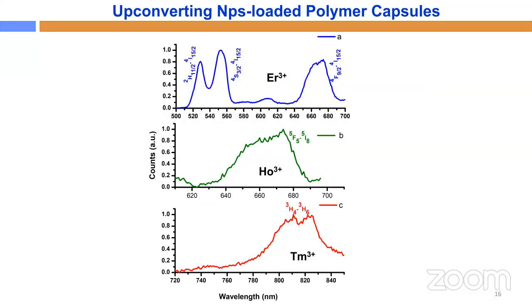Once it is done, we have done the fluorescence emission spectroscopy. We found, excited with 980 nanometer, that is the near infrared, we get the emission in the visible region, that is an upconverter. Erbium gives the green and red, holmium gives the red, and thulium gives in the near infrared region. That is a very, very important one because excitation is in the near infrared and emission is also in the near infrared. That is a very ideal case for bioimaging.